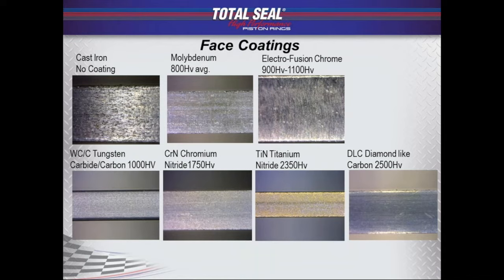Lake had talked about it a little earlier in his presentation, showed you some hardness numbers. And these are some illustrations of actual ring face coatings. In the upper left, as you can see, we've got cast iron with no coating. Fairly porous area, but no anti-friction, no anti-wear, very soft material. The one I want to concentrate on, though, is the one in the middle top, molybdenum. It's about 800 Vickers hardness. And one of the unique characteristics about molybdenum is it's very oleophilic. It holds oil like a sponge.